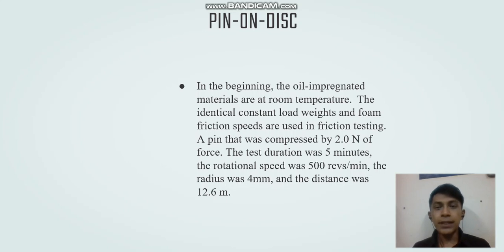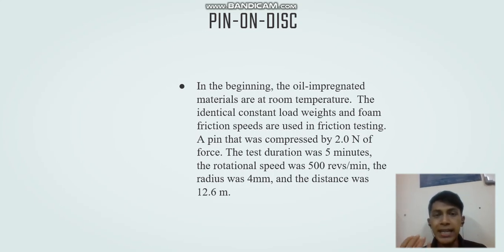Pin-on-disc: in the beginning, the oil impregnated materials are at room temperature, and then the identical constant load weight and friction speed are used in friction testing. A pin will compress with 2 Newton of force within a duration of 5 minutes, and the rotation speed was 500 revolutions per minute. The radius was 4 mm and the distance was 12.6 meters.